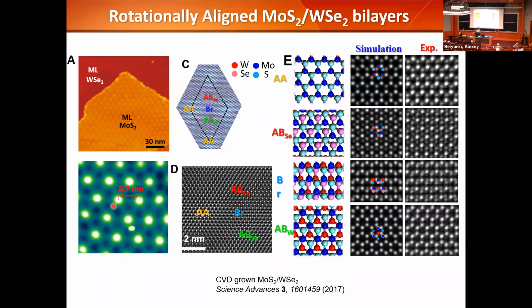So here, the chemists just start growing them in a vapor form. They heat up some powder, and they would just energetically find this structure that's energetically favorable. But I don't know how to do that. We literally take material and we stack them. We can rotate them because the van der Waals force is very weak. Now I can even simply control the size of the quantum box by twisting the angle. That's what we do. But this is what nature does, because the atoms are allowed to settle down at minimal energy states. They can still form this very well-defined checkerboard of Moiré superlattice.